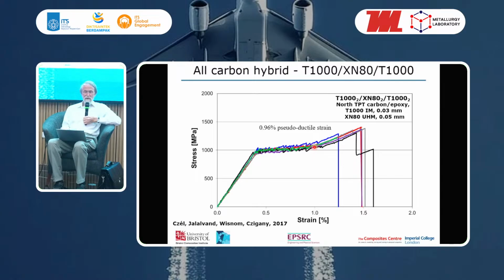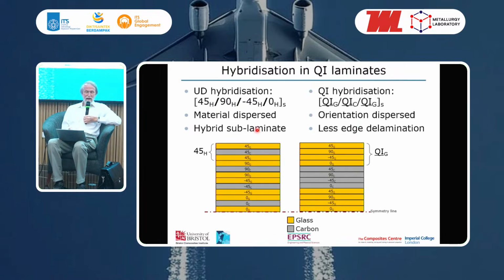So we hybridize carbon glass laminates, and there are two ways you can do the hybridization in this quasi-isotropic laminate. A quasi-isotropic laminate has the same stiffness in any direction, and that can be achieved by having 45, 90, minus 45 and 0 plies with the same thickness of each. There are other ways you can do that with a 0 plus or minus 60 or other combinations of angles. In this case, we're doing a 45, 90, minus 45, 0 layup, and you can do it in two ways. You can either take each sublaminate and put one carbon ply between two plies of glass at 45 degrees, do the same at 90 degrees, the same at minus 45 and the same at 0.